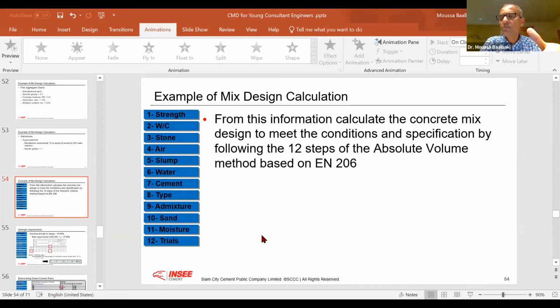Supplementary cementitious material, when you talk about slag, fly ash, silica fume, pozzolan, limestone, burnt oil shale, calcined clay. These are all materials that can substitute the clinker, and they participate in what you call a pozzolanic reaction, or a filling effect reaction, which is physicochemical, to provide you a certain resistance. When I say resistance, I mean compressive strength, for example. And at the same time, they also improve your permeability.